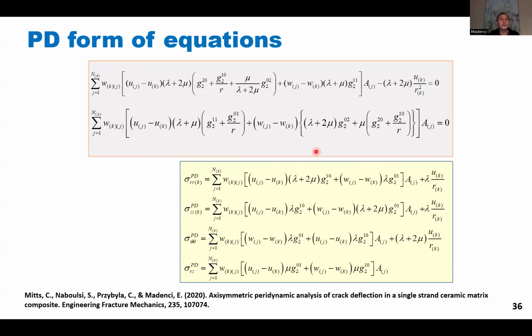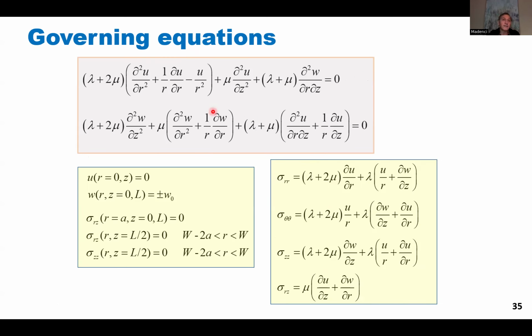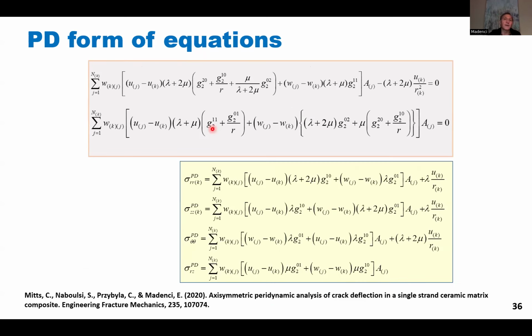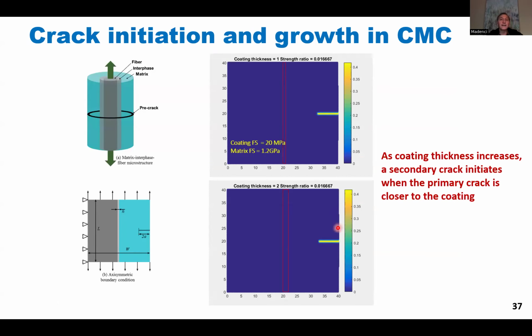Then we rewrite all of these equations using the peridynamic differential operator. And these are my peridynamic functions, right? We write everything in terms of the unknowns, the displacement components U and W. U is the displacement in the R direction, W is the displacement in the Z direction. These are my stress-strain relationships. And here you can see the crack initiates before it reaches the interface, you have initiation, and then they coalesce, and then they propagate through.